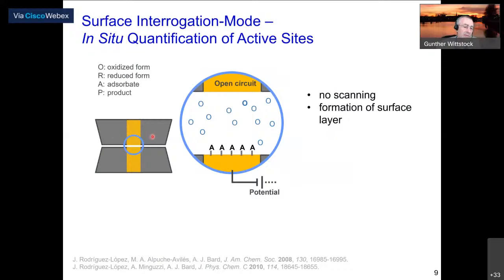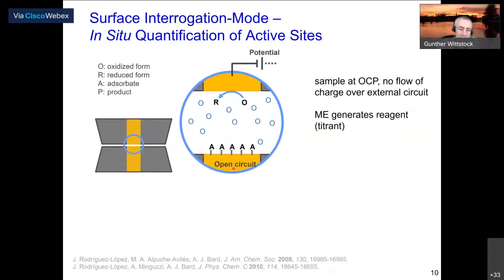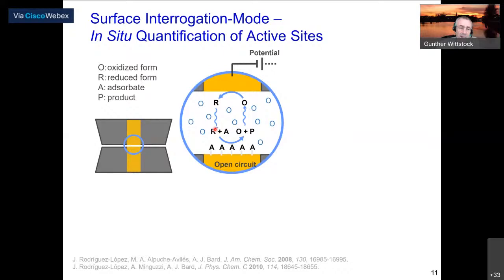So how is this procedure done? We use the normal imaging modes to align the two microelectrodes one over the other. Once we have reached this collinear alignment with a small distance, then we can start to apply a potential program to our sample electrode and to create a defined surface modification. So for a noble metal, it would be a surface oxide. Then at the next step, we disconnect our sample from the external circuit. So now everything that was formed here cannot react by electrons moving out to an external circuit. It can only change by reacting with solution components. And in that moment, we start to form a reactant at our interrogator electrode, and that reactant diffuses to the sample and then can chemically react with the adsorbates or the surface oxides. It basically titrates the surface layer.